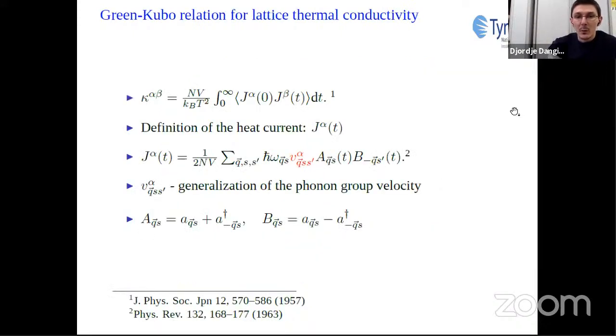Well, we start from the Green-Kubo expression for the lattice thermal conductivity. Here, kappa is the lattice thermal conductivity, and V is the volume of the simulation cell. T is the temperature, k_B is the Boltzmann constant, J is the heat current, and the brackets here mean the heat current gets autocorrelated. First, what we have to do is to define a heat current J.